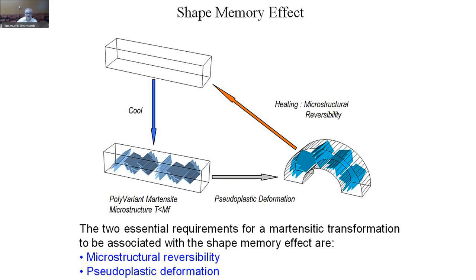And when you cool it, you'll get the polyvariant martensitic microstructure, and when you deform it, you'll get the pseudoplastic deformation. Something happens, and you have this macroscopic shape change. But when we heat it, we get back to the austenite, or how it was shaped in that hot condition, or thereafter, if you have machined it into some shape, whatever it was in that condition, you'll get back to that. So the two important parts of this shape memory are pseudoplastic deformation and microstructural reversibility. These two parts give rise to the entire shape memory effect. It has to show you a deformation which does not matter, which can be sort of undone. And then when you do microstructural reversibility, it gets back to its original form.